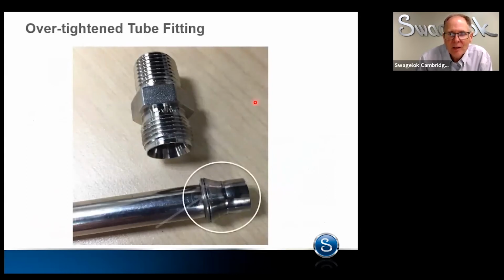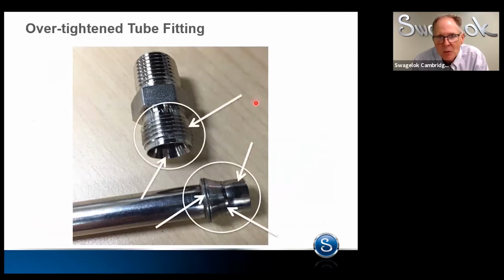Here is just an example of an over-tightened fitting. And you want to pay attention to this. If you over-tighten a fitting, there's a couple of checks for it. Now, initially, you'll get a good seal. You take it apart, and that's where the problem possibly could arise. One of the things that you'll notice here, at the end of the tubing, right here. Again, we swage the tube. The tubing ahead of the ferrules is slightly enlarged. This is an important feature because that fits into the ID of the fitting. This absorbs vibration away from where the seal takes place.